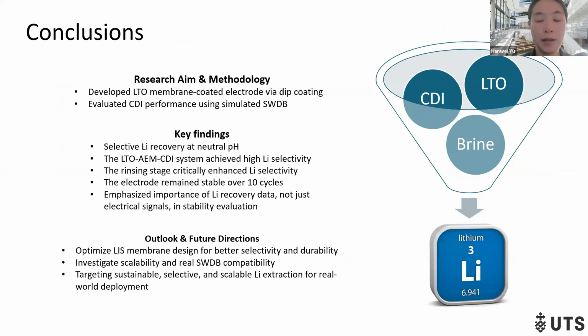Here's the brief conclusion of this research. In this research, I developed an LTO membrane-coated electrode via dip coating and evaluated its CDI performance using simulated seawater desalination brine. The key findings include: it achieves selective lithium recovery at neutral pH, and the CDI system achieved a very high lithium selectivity. The rinsing stage critically enhanced the lithium selectivity. The electrode remains stable over 10 cycles, and it emphasized the importance of lithium recovery data, not just electrochemical signals, in stability evaluations.